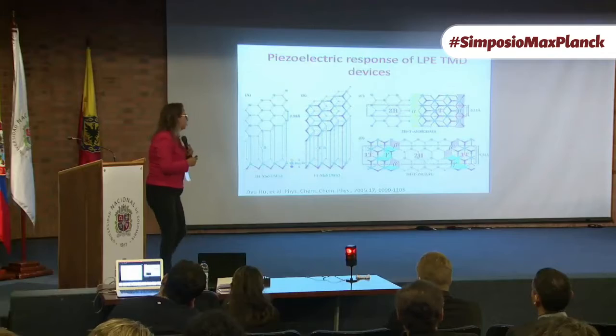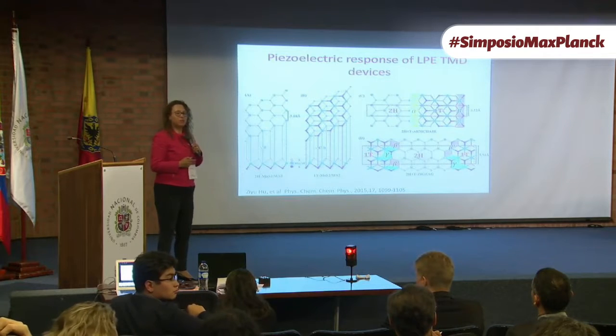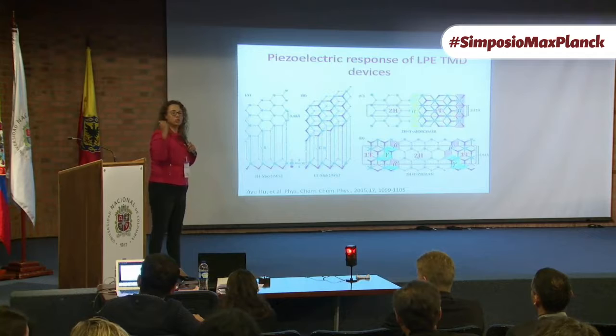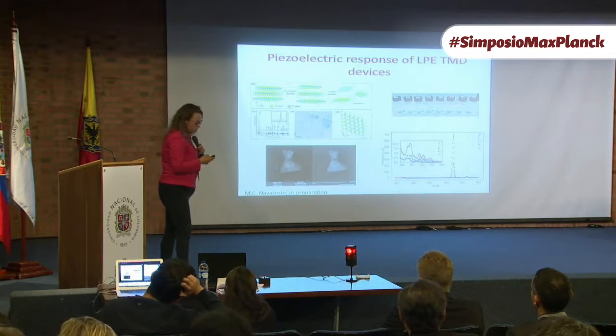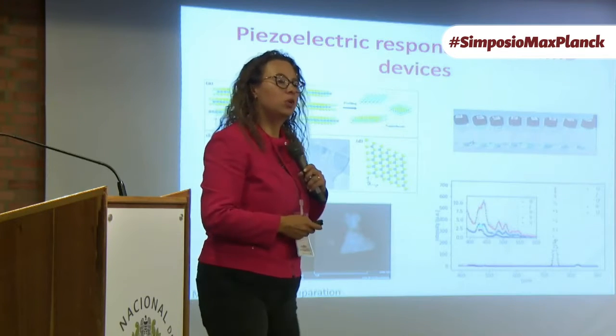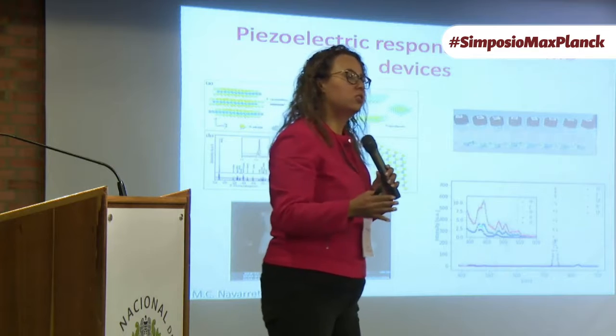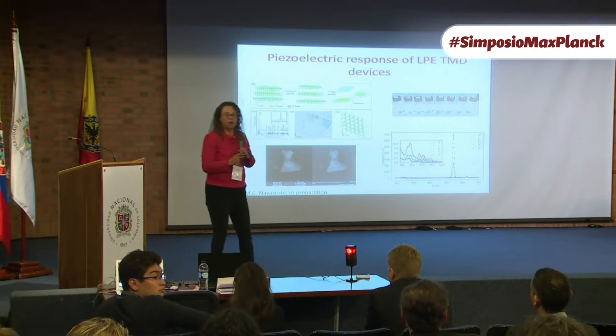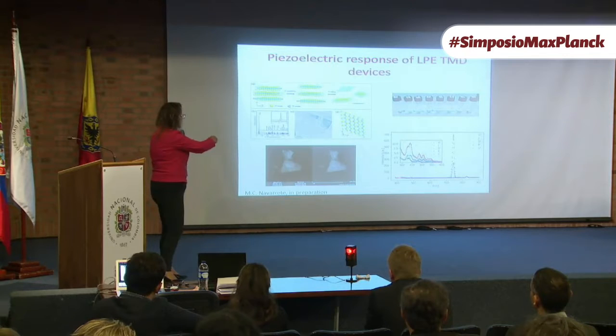Lastly, with two minutes remaining, we decided to try those 2D materials — in particular molybdenum disulfide (MoS₂) for piezoelectrics. With piezoelectrics you can harvest a potential through a mechanical force, and you can do this with MoS₂, because when you exfoliate it in odd-numbered layers it is piezoelectric. We inferred this because odd-layer-numbered materials are not centrosymmetric and induce second harmonic generation on the surface. This is MoS₂.